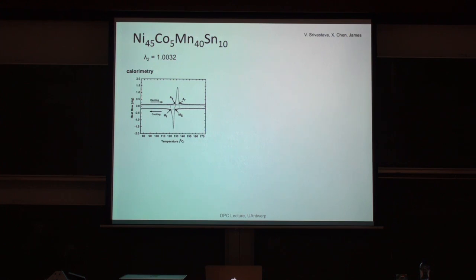Heusler alloys have chemical composition A2BC. The original Heusler alloys had the property that if none of A, B, or C are ferromagnetic in the periodic table, then you make A2BC and it's ferromagnetic. So they have a great propensity towards ferromagnetism. Even if you go off stoichiometric, this is maybe based on nickel 2 manganese tin, and it's even pretty far from stoichiometric, but still. So we managed by changing composition to get lambda 2, not that close to 1, but anyway, had about 6 degrees hysteresis, that's calorimetry.